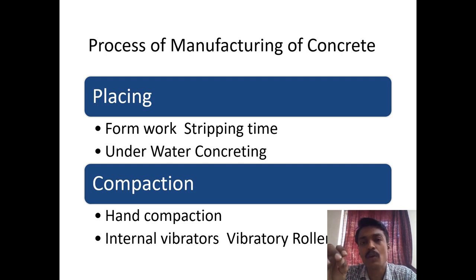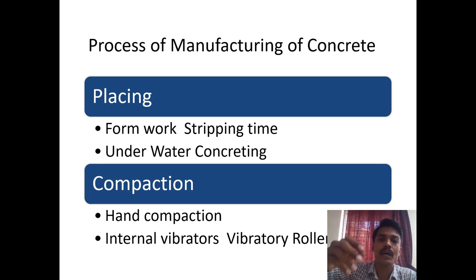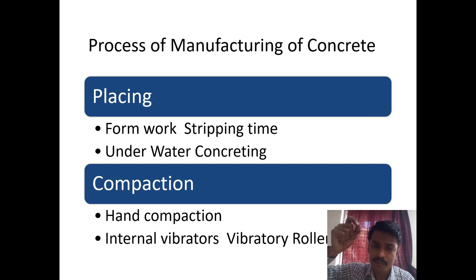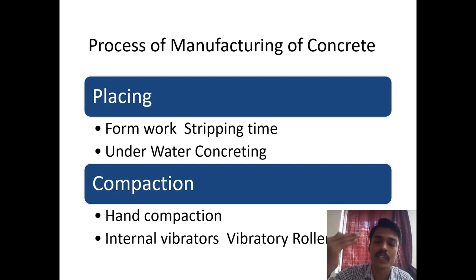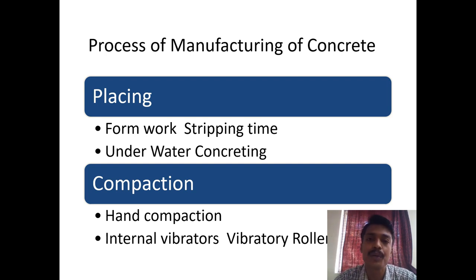What we should do is, depending upon the height of the vibrator being used, first pour concrete to one level, vibrate or compact it, then pour the next level and compact again. In this way, the compaction works very well and at the same time prevents honeycomb.